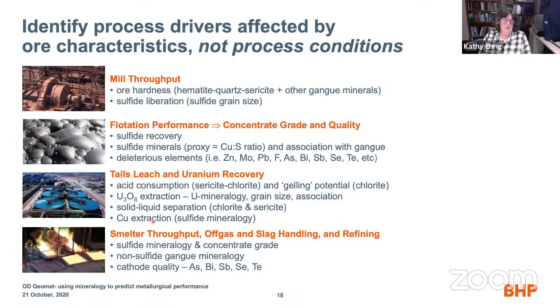In the smelter, we have to worry about throughput. The purpose of smelting is to separate the metal, which is copper, from iron, which goes into slag, and the sulfur, which is part of our off-gas stream. That off-gas stream we capture and make sulfuric acid, which we use for our leaching circuit.